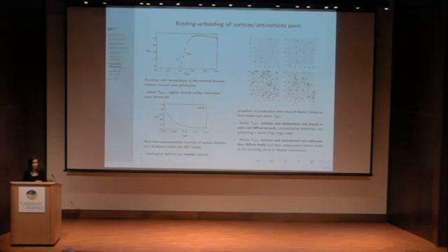So to assess whether we are in the presence of such dynamics, although this part is still at its preliminary stage, we have done some molecular dynamics, and we have computed, for instance, the real-time autocorrelation function of the spatial distribution of defects within the BKT phase, here shown. And we see that this autocorrelation with time features a decay, which signals that the topological defects are mobile entities. They diffuse. So here I present two snapshots that are consecutive in time, below T_BKT and above T_BKT.